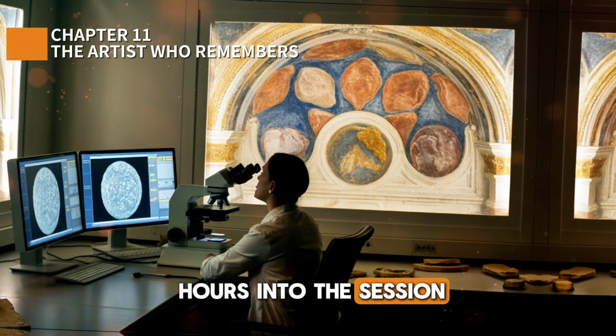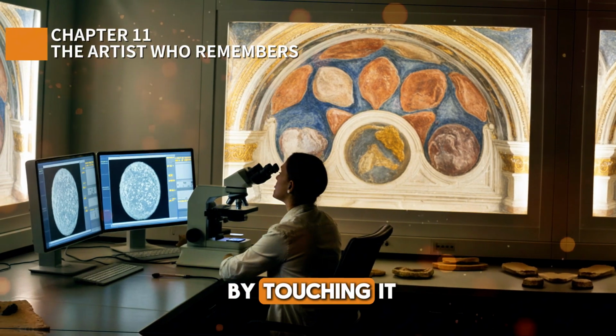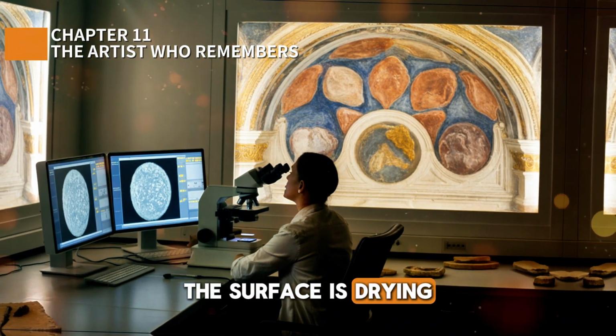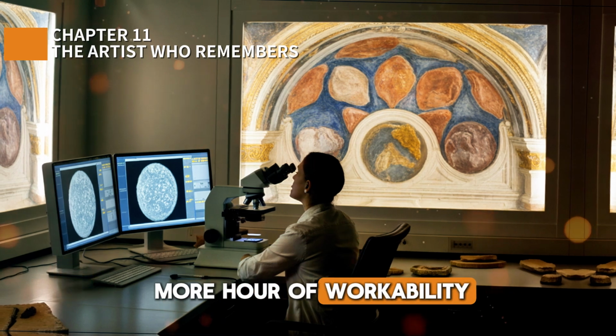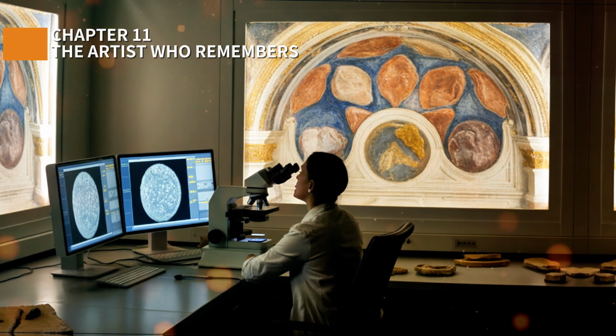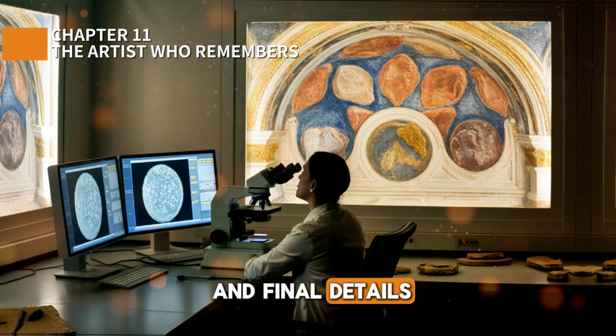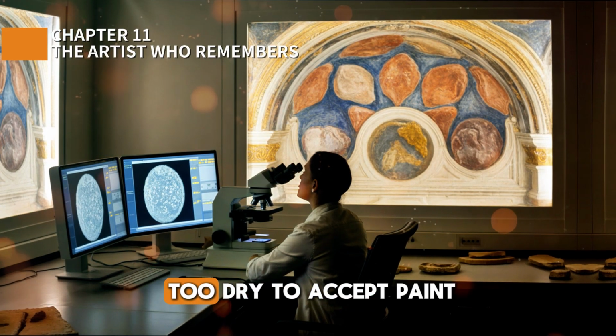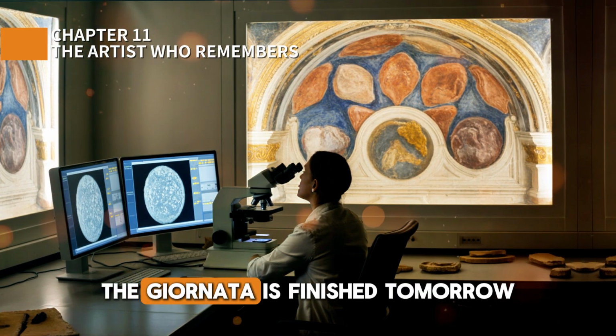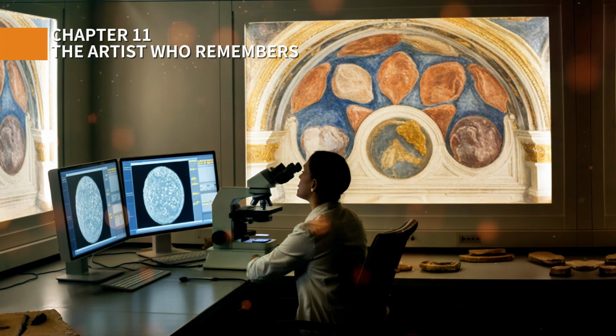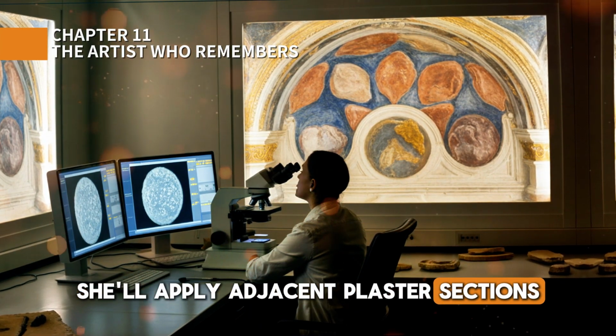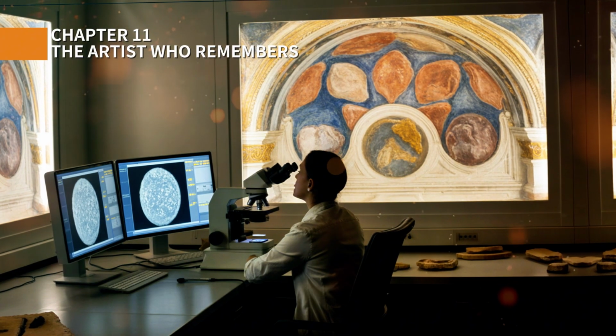4 hours into the session, she tests the plaster by touching it. The surface is drying. She has perhaps 1 more hour of workability. She accelerates, completing the figure's face and final details before the plaster becomes too dry to accept paint. The giornata is finished. Tomorrow, she'll apply adjacent plaster sections and continue the composition.